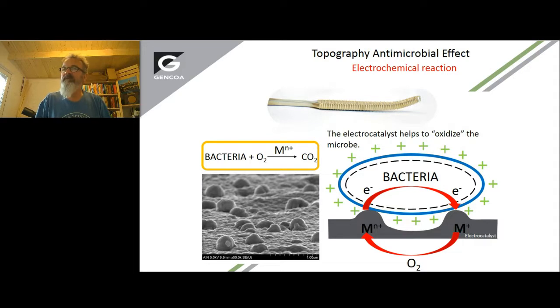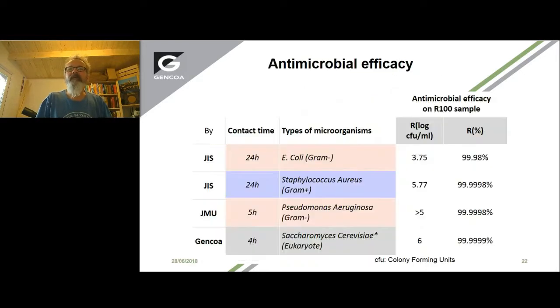And actually what we're doing is really mimicking nature here. That's a wonderful thing to do. There are lots of natural surfaces that are antimicrobial, and we are just using our knowledge of physics to try and reproduce what nature is doing. We've had our surfaces tested at various different laboratories under various different standards, but the important thing to note is that we're seeing kill rates of up to about log 6 within a couple of hours. So these are very, very active surfaces. We've looked at various different microorganisms.